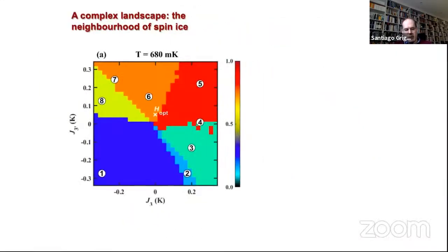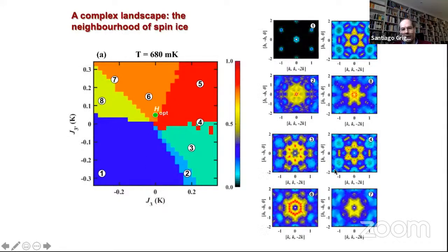So essentially what this method allows you is to get a nice effective Hamiltonian to describe this material, but it also gives you more information. The first thing, as I said, is that you get information about how to create new materials, and the other is that it tells you not only where your system is, but what happens in the neighborhood of your system. So I'm showing you here the parameter space J3 prime, and this point here is where dysprosium titanate sits, right? But you can see that these colors here correspond to distinct patterns in your neutron experiment. So they correspond to different types of long range or short range order that you get in this system. So small variations of these parameters make huge differences in where you sit.